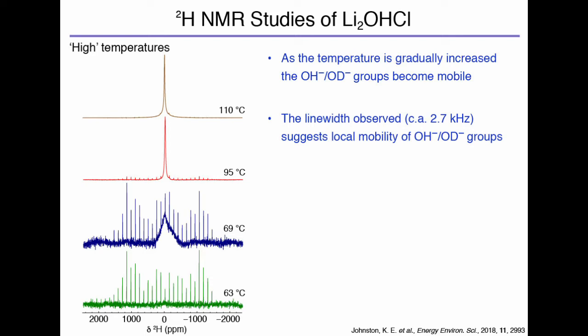Okay, so what this is telling us is we have static proton environments at 63. As we increase the temperature, we start to get gradual movement of those OH groups at 69, that's what this bit means. And then at 95 and 110, the majority of the protons are moving in some way, they're mobile. But what's quite important to note here is that you still have the presence of these weird sidebands at 95. You can't see them in this 110, but they are in fact there as well.